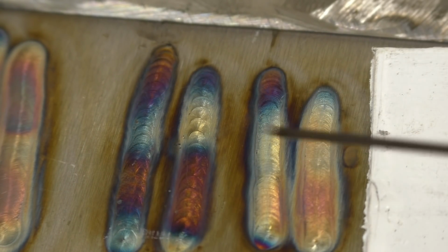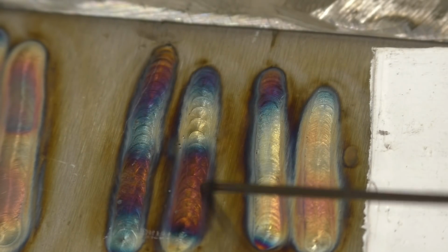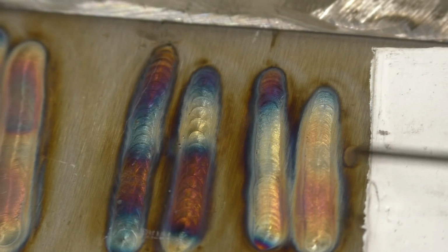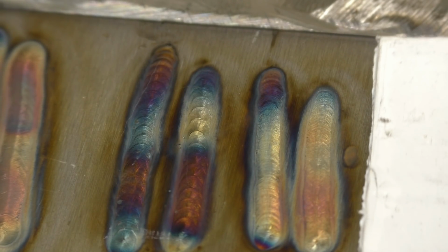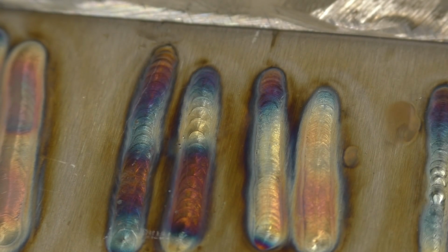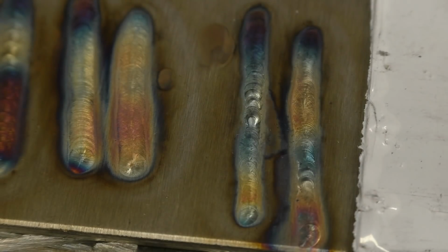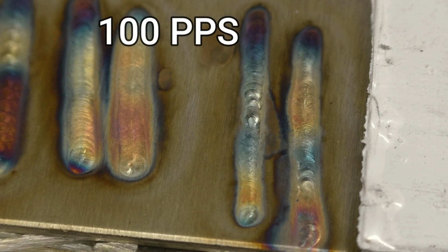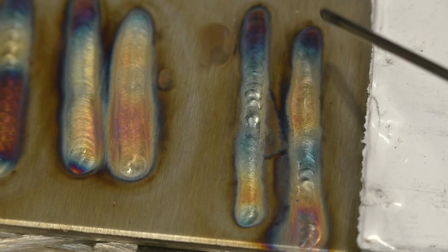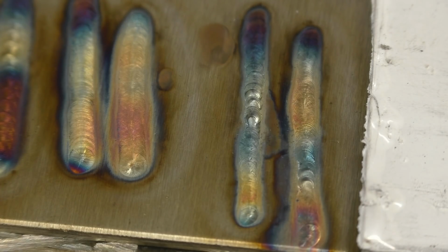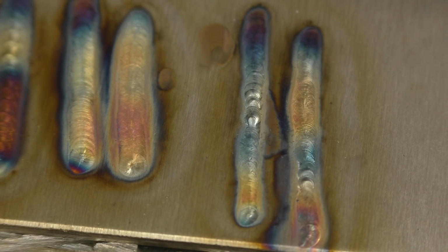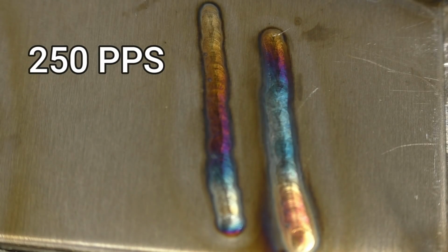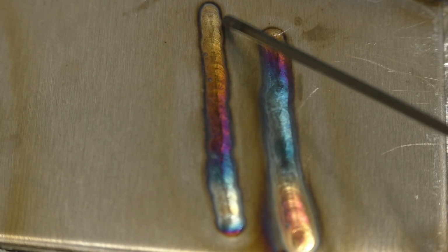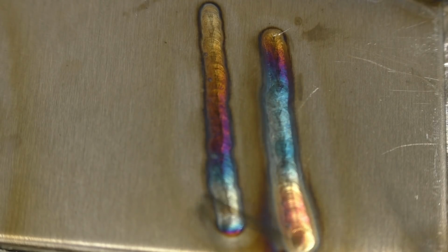The heat affected zone is a lot less than these ones, has more heat dissipation than there is on that one. Go along again. Next one, 100 pulses a second. See the arc's even tighter and there's less heat affected zone around the weld. And then finally we'll come up to that's 250 pulses a second, still on 80 amps. And you can see there's hardly any heat affected zone around it. The arc is much tighter.